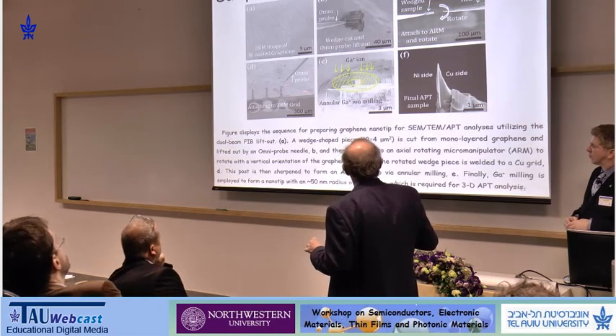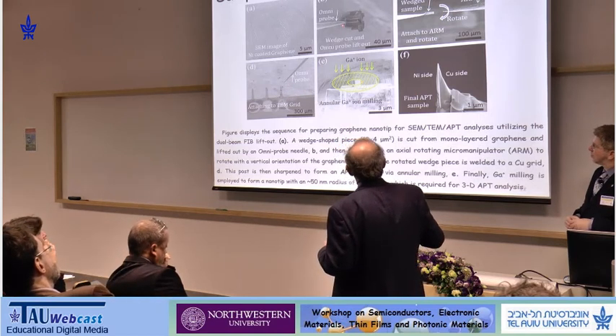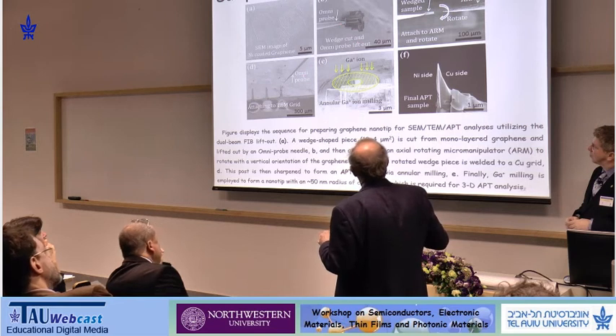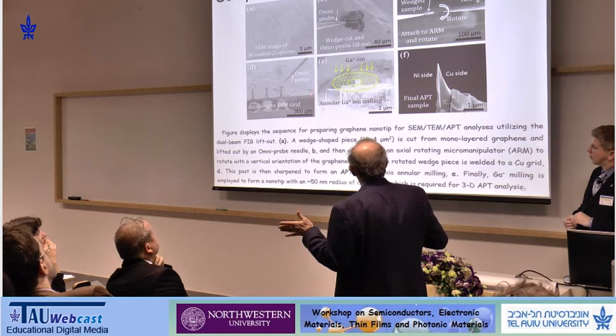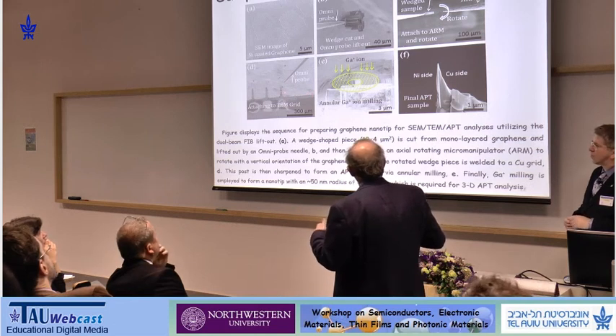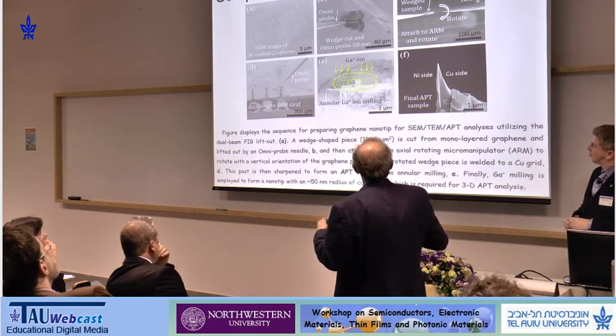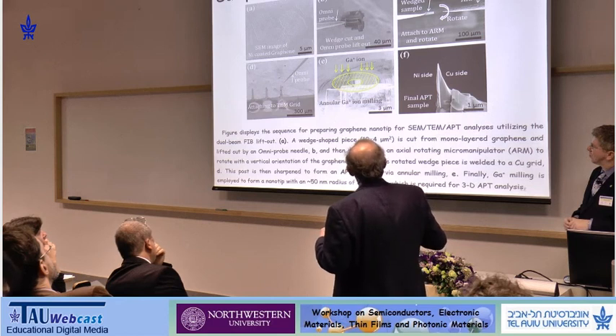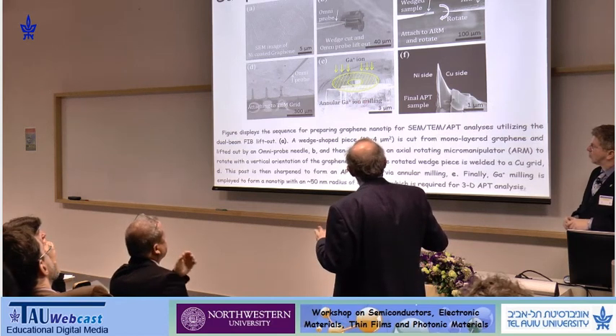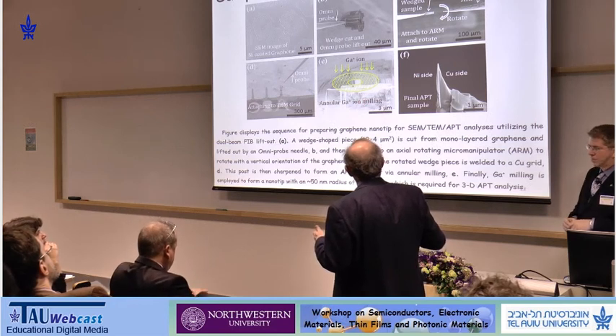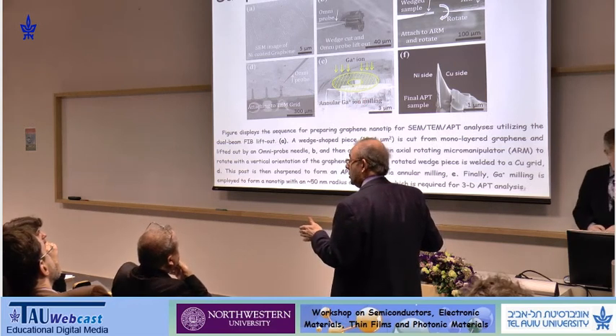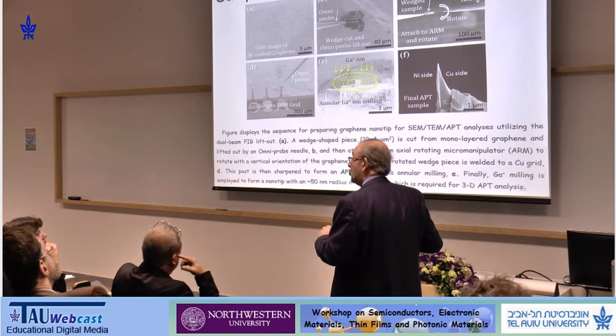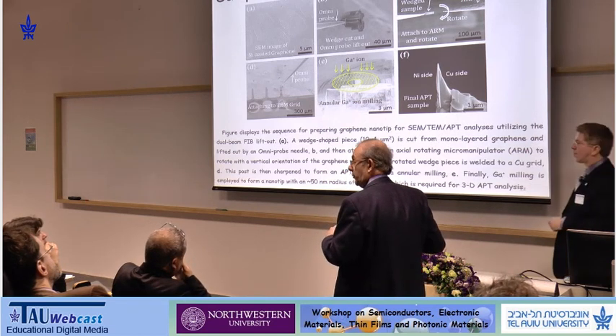And then this is how we make a tip. We do combined TEM and atom probe tomography. So we take a specimen, without going through the details, and we transfer it to a grid and look at it with the electron microscope. And then similarly, we can take the same specimen and make an atom probe tomographic tip out of it. That requires using gallium ion milling, where we start at a high energy and finish at just maybe 2 kilovolts of energy.